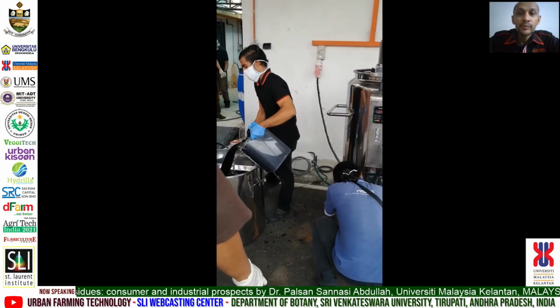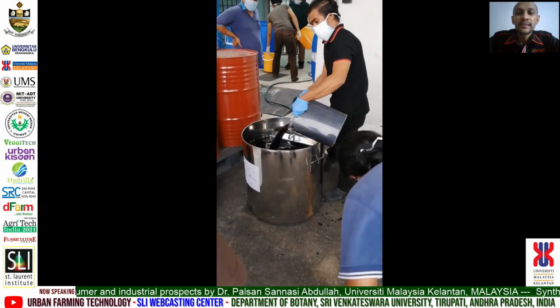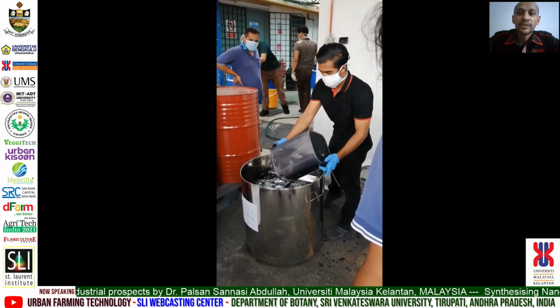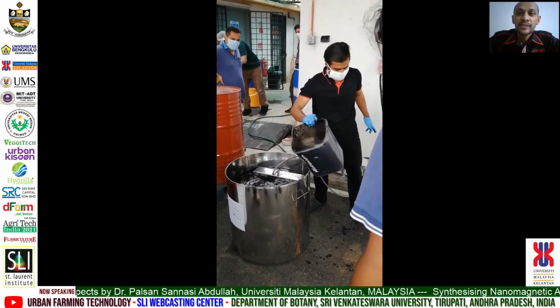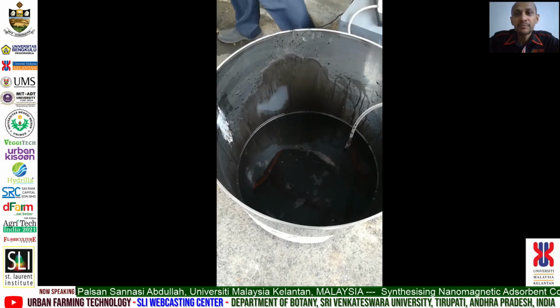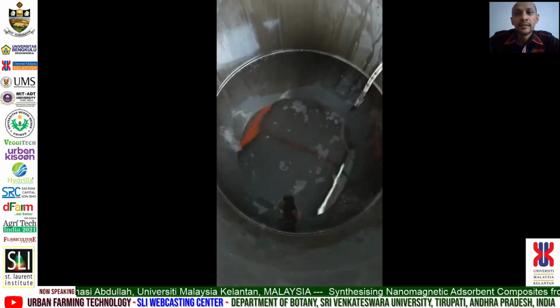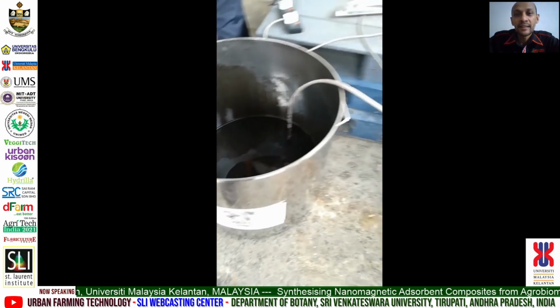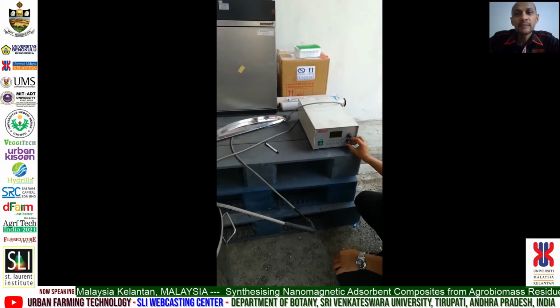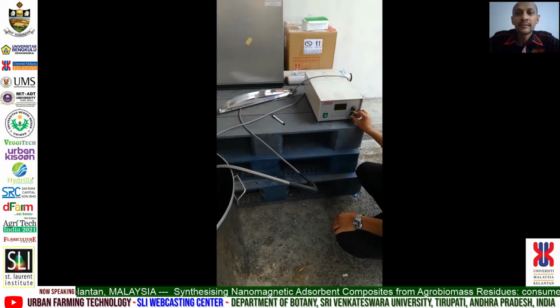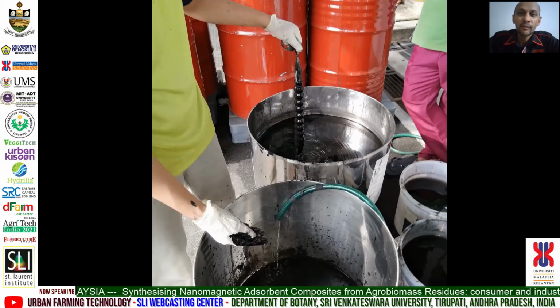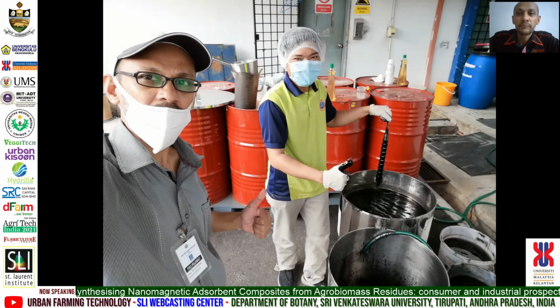Yield obtained was around 78 to 82% up to 6 kg per batch. It is essential to enhance the dispersion of the nanoparticles, prevent interparticle aggregation, and allow maximum concentration of the iron oxide magnetic nanoparticles to be in contact and attached to the biocarbon.